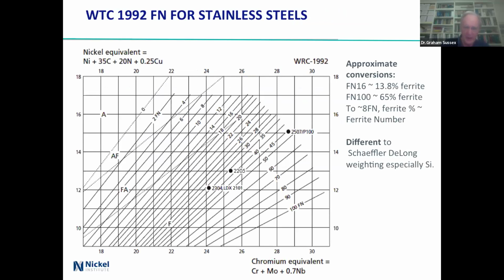But on this diagram, we're looking at the nickel equivalent and the chromium equivalent across the bottom, and what's going to happen. And on this are the ferrite numbers going across there, and the percentages are going to be different. And this is where we've got the lean, ordinary duplex, and super duplexes. And these A, AF, FA, and F are simply saying out here it will solidify as austenite, there it will solidify as austenite with some ferrite, here it'll go as ferrite with some austenite, and here it's going to be all ferrite, except it doesn't work quite that way because of where these alloys are.